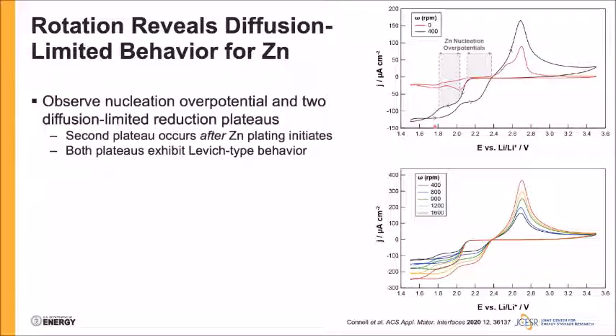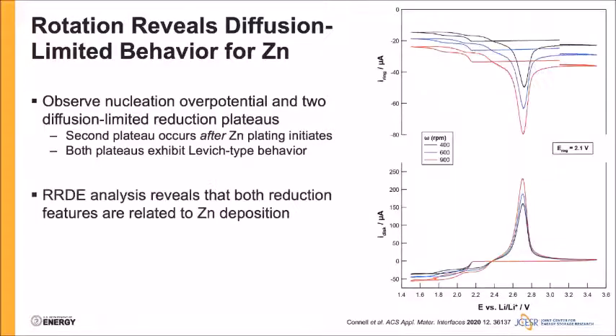What we also see is that both of these reduction plateaus exhibit Levich type behavior. So they exhibit a linear increase in the limiting current density as you go to higher and higher rotation rates. And so this suggests that definitely multiple species are active in the system. But to confirm that they are indeed related to zinc deposition, this is where the ring disc technique comes in